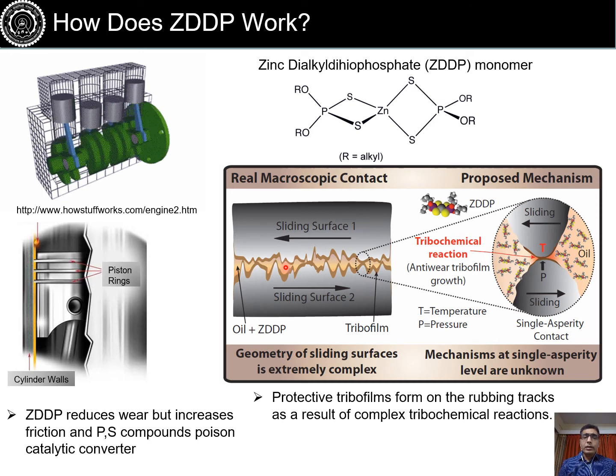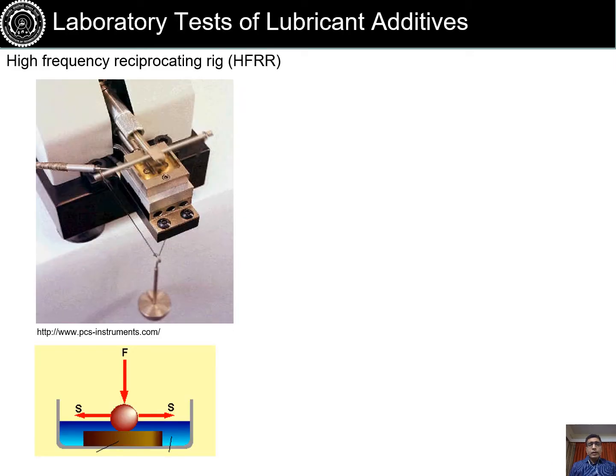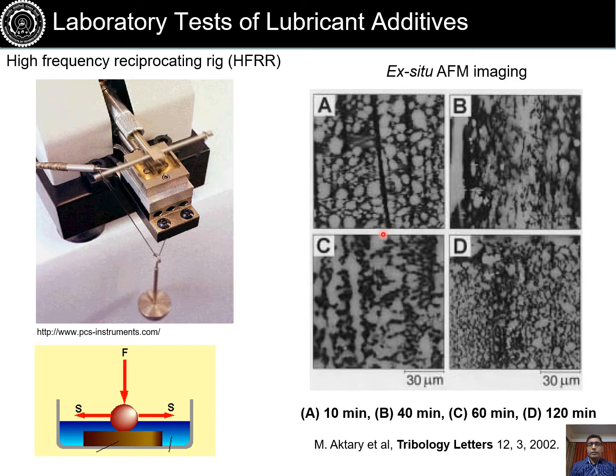which has been very difficult to interpret in terms of understanding the local interactions. So what typically people do to look at these lubricants' interaction with these metal surfaces is use tribometer tests, where they can use a metallic ball against a metallic surface. And what they have observed, whenever ZDDP is added to the lubricant, some film starts to develop in presence of ZDDP. And as the time progresses, this film becomes more dense and thicker, and that results in anti-wear properties, because now metal-metal contact is prevented due to formation of this protective layer.